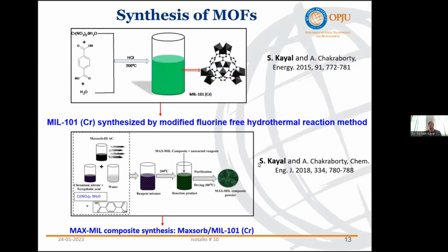So now I'll show some of the individual metal organic frameworks which I have synthesized in our chemical lab. The first one is MIL-101 chromium. For this we used chromium nitrate salt, the ligand is benzene dicarboxylic acid, and we use water as a solvent. We use 2 drops of HCl, hydrochloric acid, as a catalyst, and we heat it at 200 degrees centigrade in the autoclave reactor.